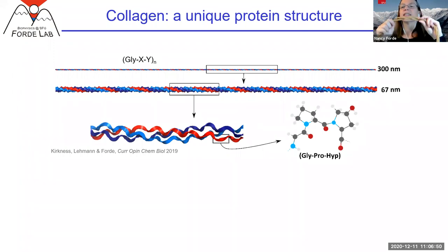I have my physicist's rubber tube model of collagen — three chains that wrap around each other tightly and form a right-handed super helix. What we're interested in is its mechanical response. The important dimensions: the contour length or total end-to-end distance along the backbone of this polymer is 300 nanometers. If you're more comfortable thinking about DNA lengths, that's about equivalent to a kilobase pair of DNA. There are three contiguous polypeptide chains that wrap around each other to make this structure.